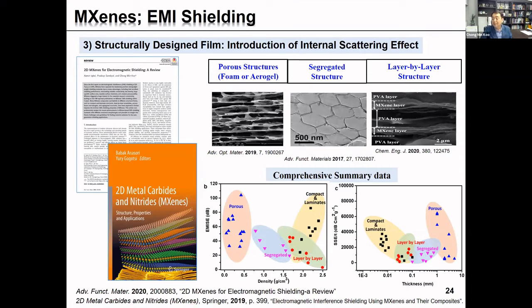The shielding performance depends not only on the intrinsic property, but also on structural design. Basically, MXene has very high shielding performance due to the intrinsically high electrical conductivity. Additionally, introduction of porous structure and segregated structure to the MXene can reduce the density and provide additional surface interface for enhancing internal multiple reflection effect. As a result, the structural design improves shielding effectiveness as well as the absolute shielding effectiveness, SSET. It indicates structural design is essential for lightweight shielding applications.